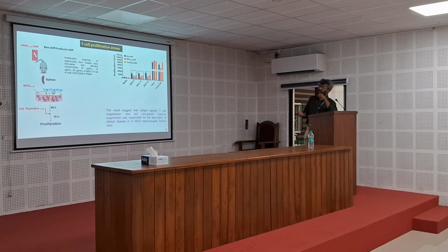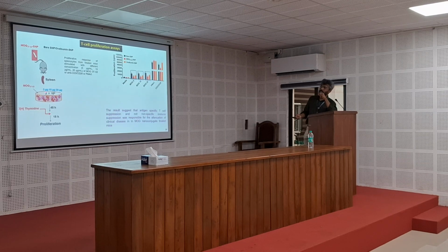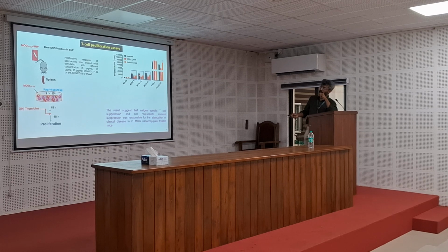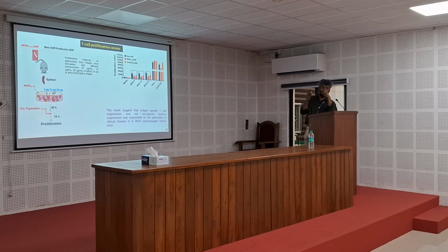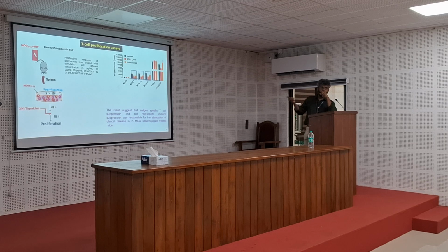We took out the spleen and tried to induce the treated mouse spleen as well as the control spleen with the different concentrations of MOG. Normally in the control one, there was severe proliferation, but in the red one, the treated one, there was a significant decrease in the autoreactive lymphocytes, the autoreactive T cells. So the proliferation was downregulated, which is again correlating with the clinical score.